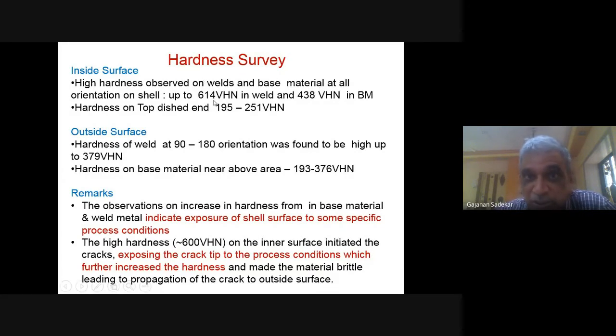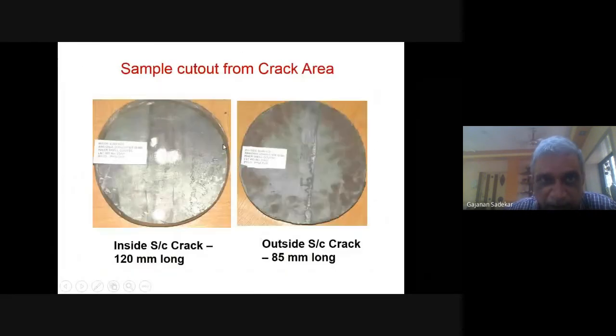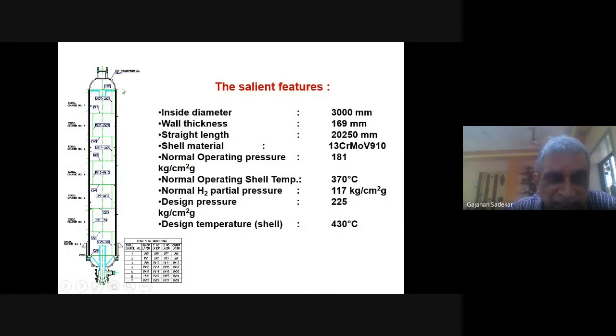This one, up to 614 VHN, and on base material at some places 438. Hardness at top dished end. Now, why it is mentioned under top dished end, I'll tell you. I'll go back to the slide. In this case, the gas enters through some internal arrangement. The gas present there will be only at 370 degrees centigrade, and this is the inlet gas, which has a different composition, and also a different temperature, because as the gas flows down, the reaction will occur and the temperature of the gas will increase. And because the catalyst is filled below this portion, that's the top dished end, there is no catalyst inside. Okay.